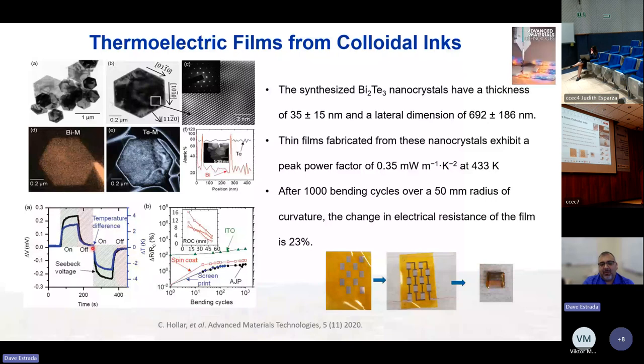And that's shown here where we put this in a temperature difference of just 4 degrees Celsius. And we see a nice voltage rise of about 200 microvolts, indicating we have good thermoelectric performance. And then we looked at the robustness of the film as printed, compared it to previous screen printed films, and show that after 1,000 bend cycles over 50 millimeter radius of curvature, we're getting about a 20% change in the resistance, which would impact the power factor.